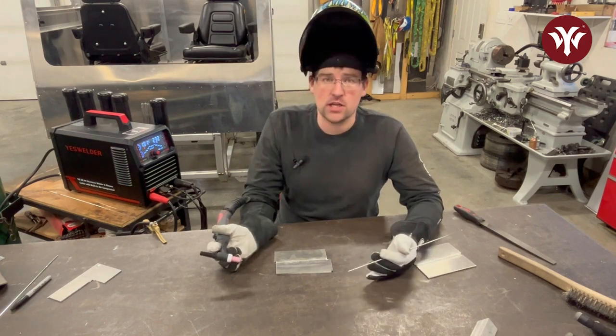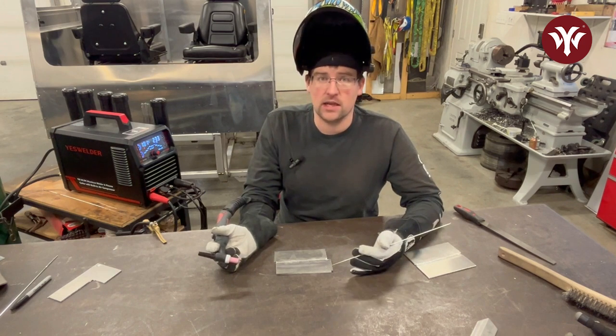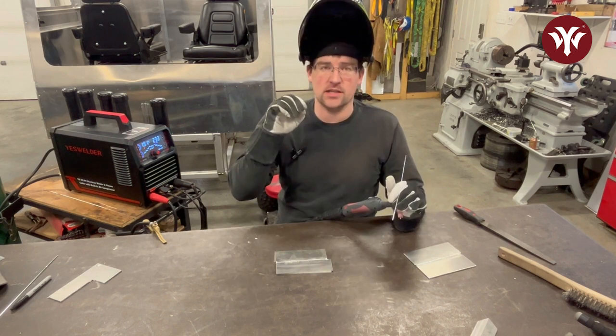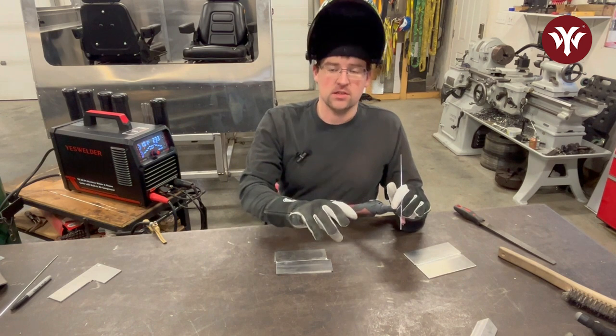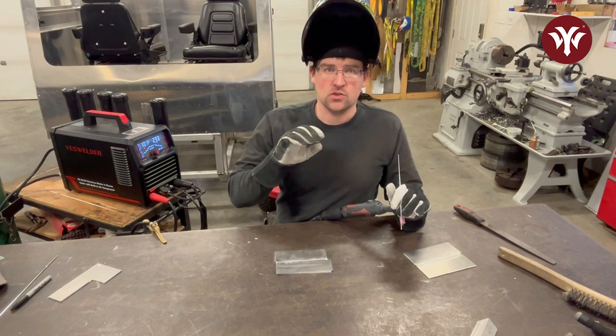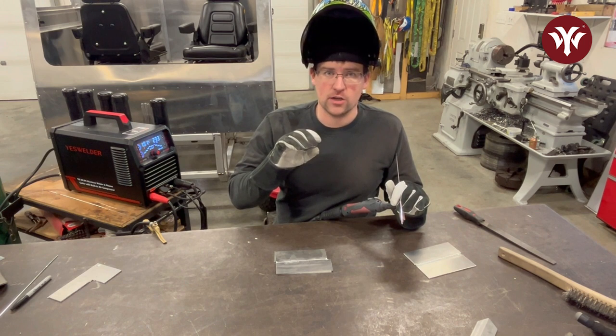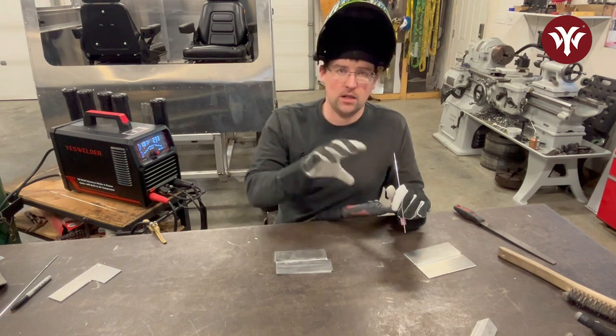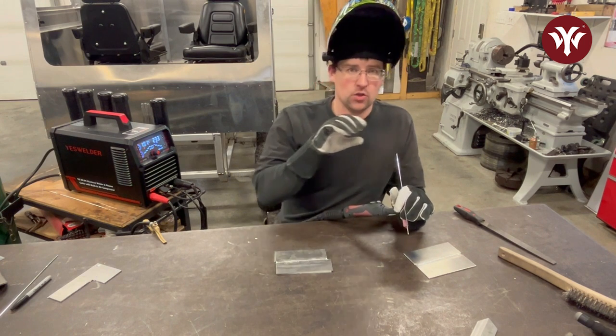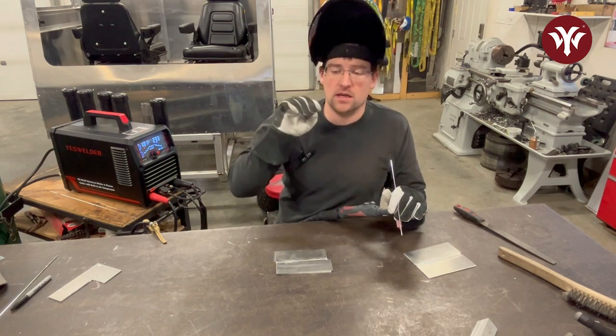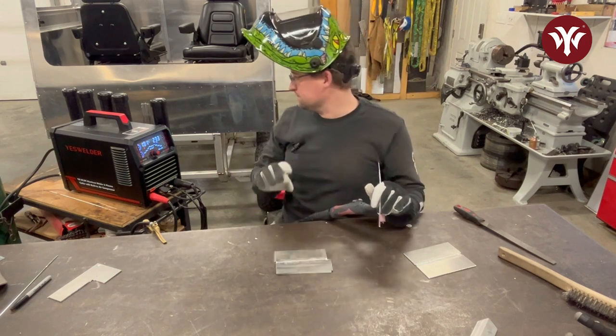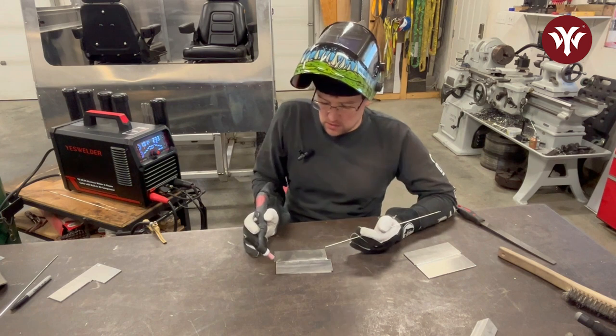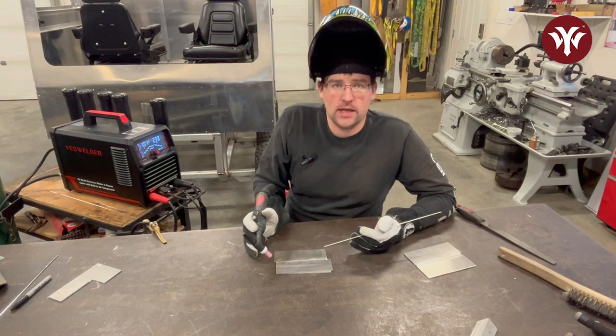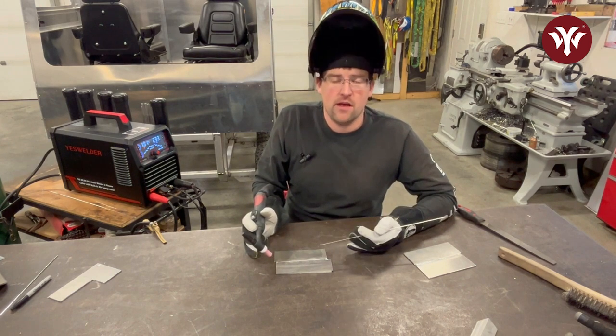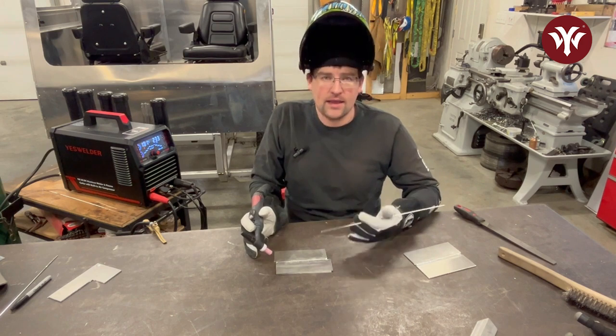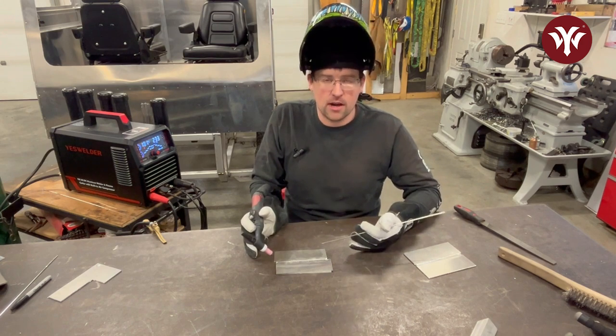It really doesn't change much from regular AC TIG welding. The only idea is that the welder itself pulses to weld and then pulls back to a maintain current, holding the arc so that you can move, and then pulse to weld, pull back to maintain, you move. So you're only welding on the hits of current. So I'm just gonna draw an arc and hold it, and I wanna see the rhythm that the pulses are developing for me. I think it's gonna be a little low, and I'm gonna need to turn it up.